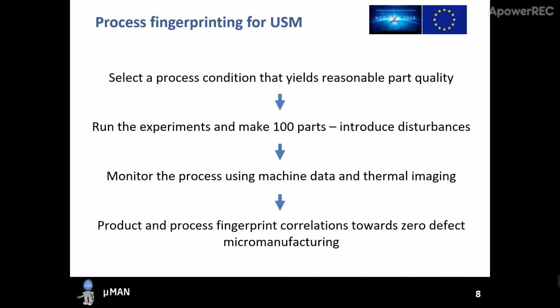The methodology for this process fingerprinting is that we first select a process condition that yields reasonable part quality, and then we run the experiments in a pilot production scenario and make 100 parts. We also introduce some disturbances, like changing the mold temperature. We monitor the process and collect all the process data using machine data, an encoder, and thermal imaging. At the end, we analyze the process and product fingerprints for zero defect micromanufacturing.